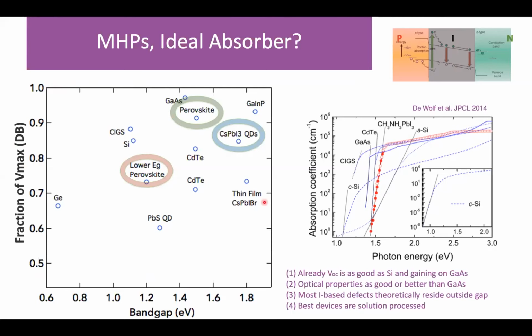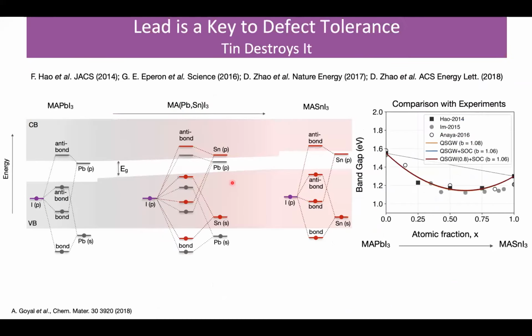And this compares a number of the different solar cell technologies, and just as you would expect, things like gallium arsenide and gallium indium phosphide, which are perfect single crystal thin film systems, do very, very well. But what's remarkable is the perovskites are very, very close in terms of this figure of merit, despite the fact that they're these horrible polycrystalline messes, which is kind of an amazing and fascinating thing.